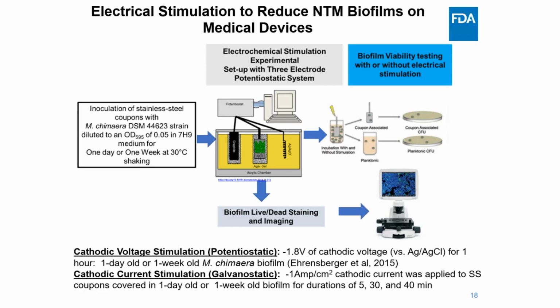We then applied two types of cathodic electrical stimulation: cathodic voltage stimulation of minus 1.8 volts versus the reference for 1 hour, or a cathodic current stimulation of minus 1 amp per centimeter square current density, applied for 5 to 30 to 40 minutes.